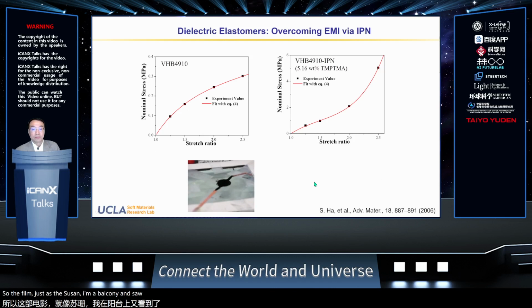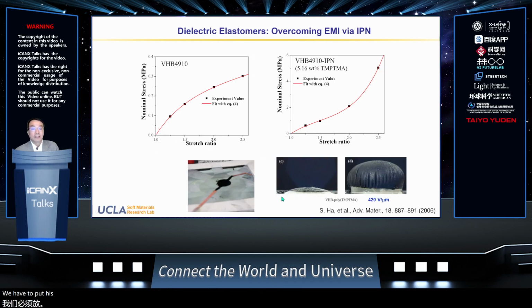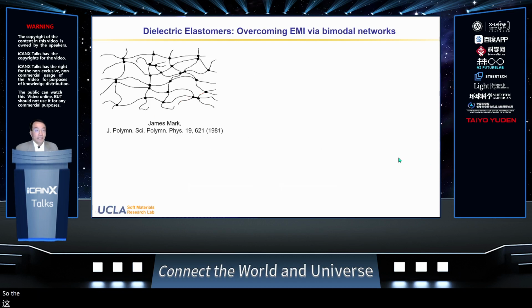Okay, so to be able to measure the area expansion of this IPN film, we have to put it on a diaphragm. This image to the left shows the film on the diaphragm. There's a diaphragm chamber behind the film, and when you actuate it, the air pressure inside will keep the film expanded. What you see here is an area expansion of over 200%. The maximum true field is 420 volts per micron, which represents a Maxwell stress on the order of several megapascals. So the IPN film also works well, and there's another way to do it.